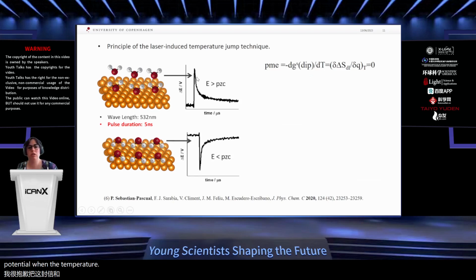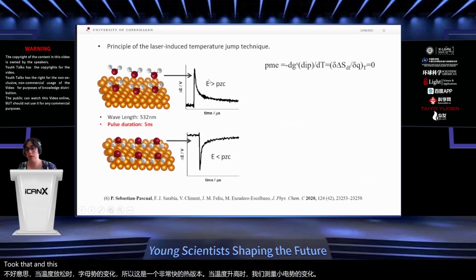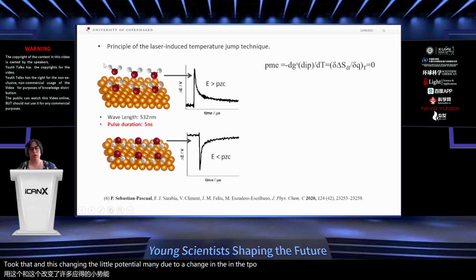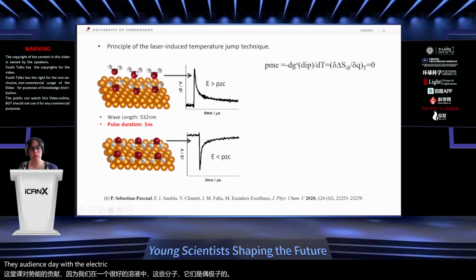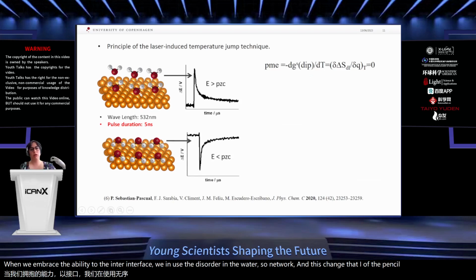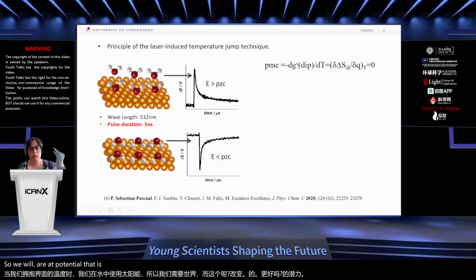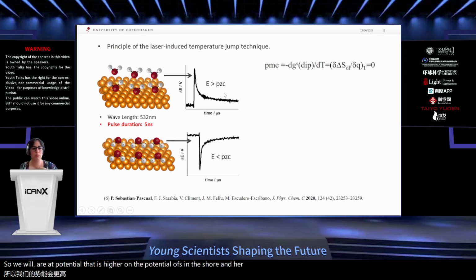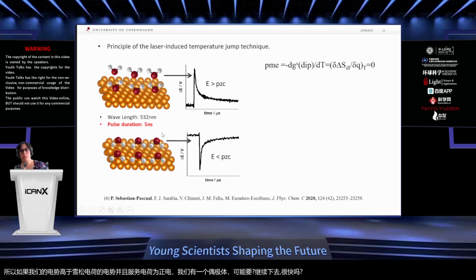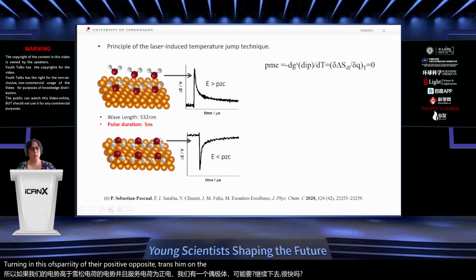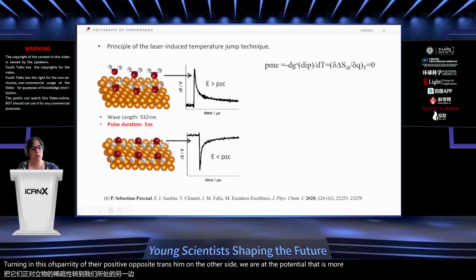This change in the electrode potential is mainly due to a change in the dipolar contribution to the potential of the electrode, because we are in aqueous solution, and water molecules are dipoles, they orient with the electric field on the surface, so they contribute to the electrode potential. When we increase the temperature of the interface, we induce disorder in the water solvent network, and this changes the electrode potential. So if we are at a potential higher than the potential of zero charge, and the charge on the surface is positive, we have a negative dipolar contribution, and in this experiment we obtain a positive transient. On the other side, if we are at a potential more negative than the potential of zero charge, the dipolar contribution is positive, and we obtain a negative transient.